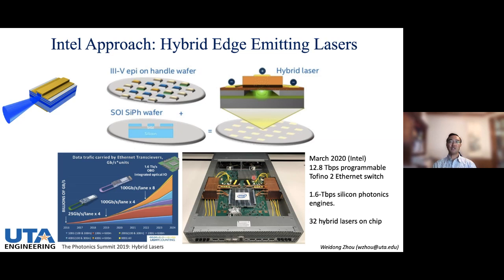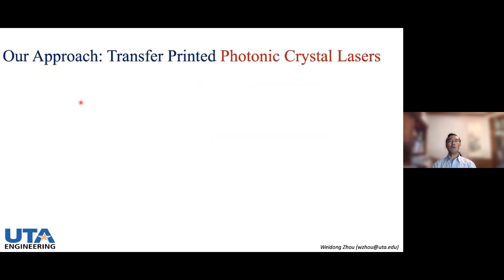However, there are different issues as well, we argue. One is that the wafer bonding process is not necessarily the best approach for integration here, because you have to do wafer bonding and then you have to remove the substrate. So that process, I think, is not ideal. Secondly, as we will see later on, energy efficiency could be an issue because the intrinsic cavity size is very large.